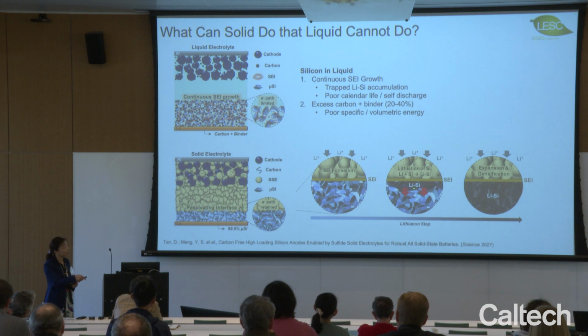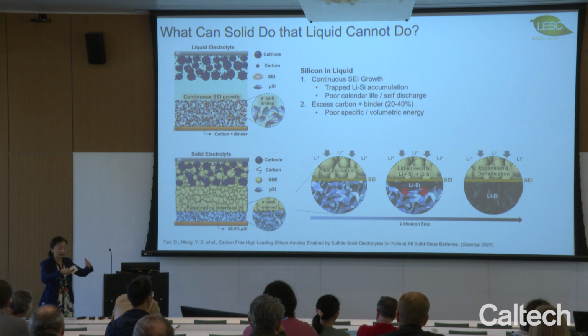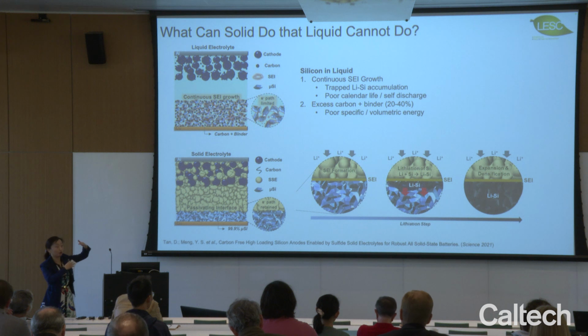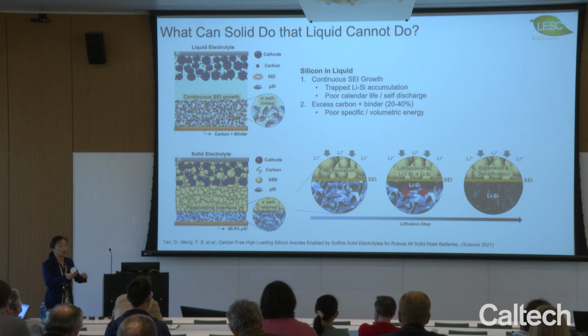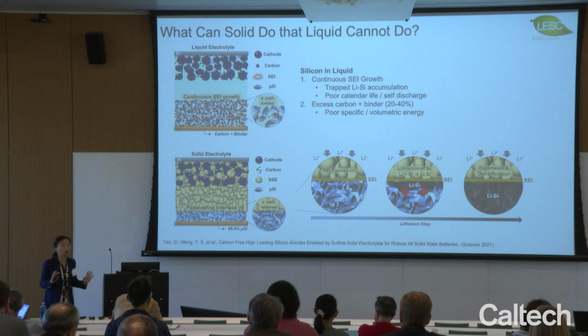So what happens to lithium silicon is that the volume will expand, but it will expand in the pores completely, plus some volume expansion. Of course, there will be some volume expansion. And this process will produce 100% dense lithium silicon alloy that you cannot get in liquid cells. So that's the thought experiment.